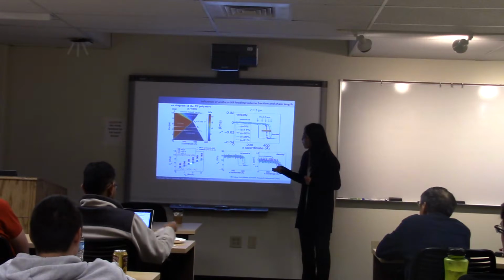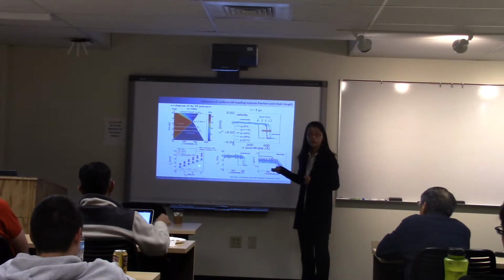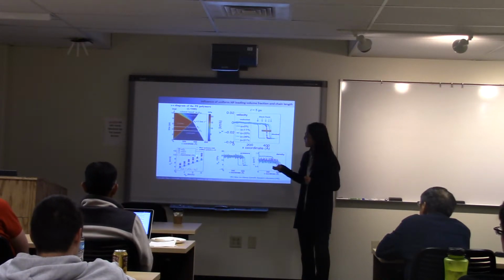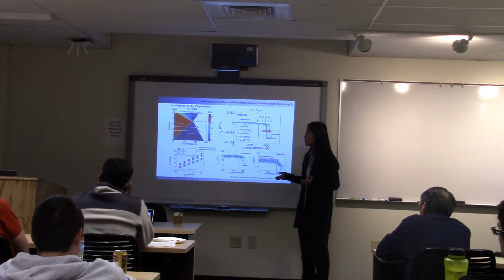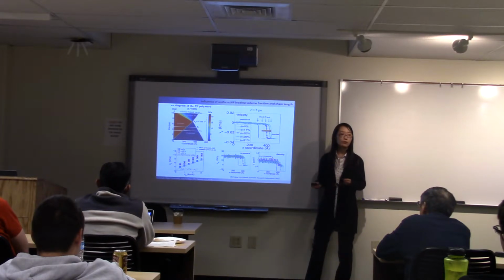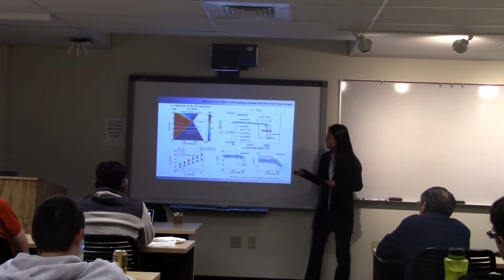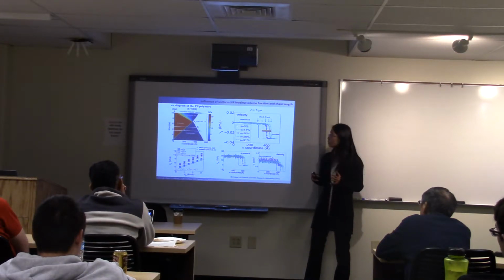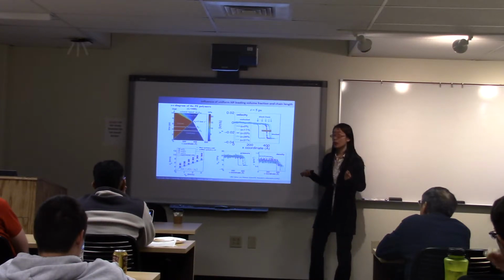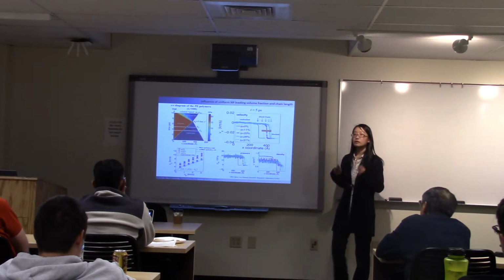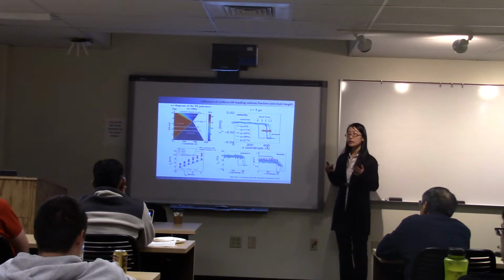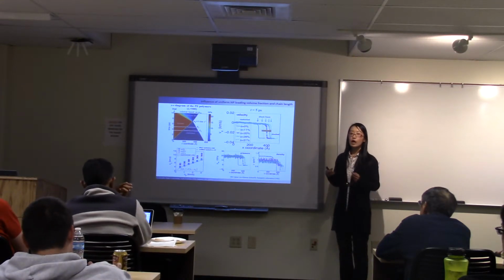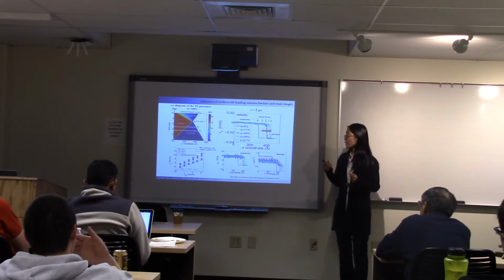We also compare our simulation results with these experimental results, indicated by the dashed line, and found really good agreement for the pure polymer without any nanoparticle addition. We found that increasing the nanoparticle loading volume fraction and increasing the chain length also increases the shock wave propagation speed, which is understandable because the shock impedance is increased by the nanoparticle and